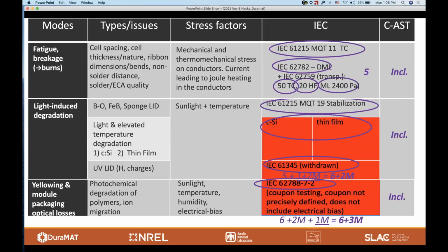The second answer is, combined accelerated stress testing does find other failure modes; you can use other tests to determine the failure modes, but in fact, quite a number of them are required. For example, if you want to look at fatigue, breakage, which can eventually lead to burns, you need 5 different tests. And that's really included in combined accelerated stress testing. Light-induced degradation: you have an additional one. If we do the sum total, we have 6 existing tests plus 2 missing tests.